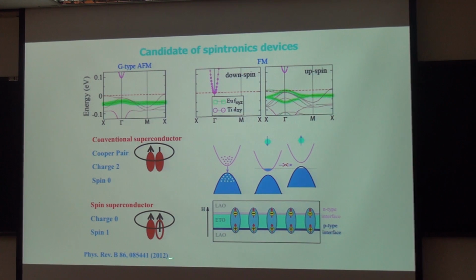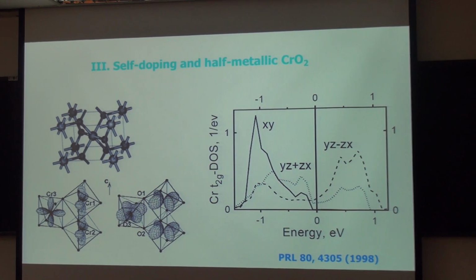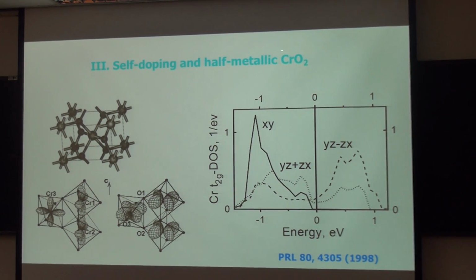According to a recent theoretical paper, if the electron and hole are spin polarized with the same spin direction, we will have the chance to become a so-called spin superconductor. That is, at low temperature, if such condensation happens, the spin transport will be dissipationless. So using superlattice structure of transition metal oxide, we have also realized dissipationless transport of the spin current. The third example is the so-called half-metallic chromium dioxide.